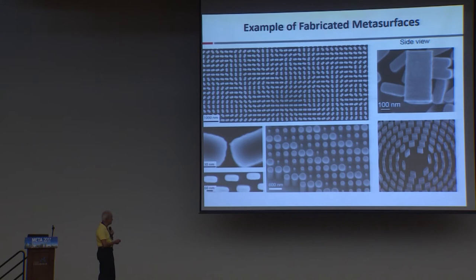So you want to minimize, completely eliminate any crystalline inclusions. So this is going at 90 degrees centigrade. If you do that, you get a highly reproducible process. These are different metasurfaces that we made. This is a generic one. This is part of a lens. This is very interesting. This is a spin-to-orbital angular momentum converter, which creates a vortex state. And we have shown we can make vortices up to very high orbital angular momentum, up to 15, actually 20. But I'm not going to talk about this today. And the key point, you see, this is a pillar, a fin that was knocked off. You get absolutely very low roughness. It's less than a nanometer roughness.